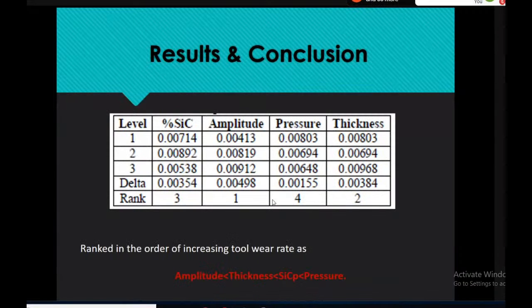Now this was the result for that experiment: the percentage of SiC is more effective than the pressure for the tool wear. It means if you increase the brittleness of the material, it definitely affects the tool wear. This means that if you machine composite material, the tool wear will definitely be higher. As we are talking about the composite, where the reinforced particles are not distributed properly, that is not homogeneous, which is why we take the orthotropic or anisotropic property of that material. So the percentage of SiC falls at the 3rd rank, while amplitude was the highest variable affecting the tool wear, then the thickness, then silicon carbide percentage.